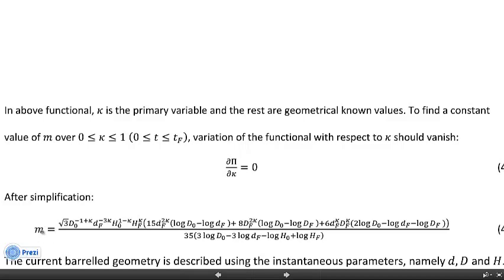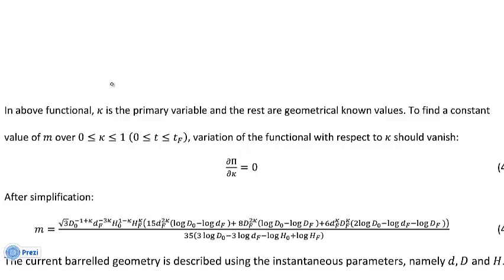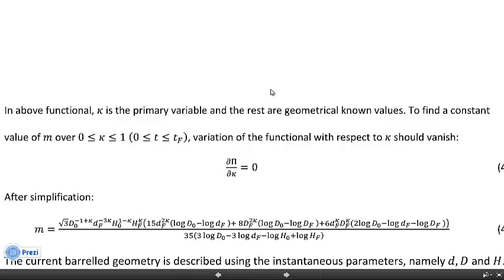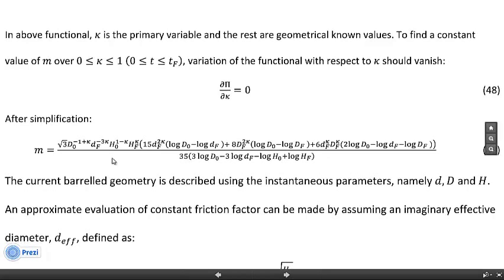We are now more confident: we have the value of M, and we have a solution to correlate the axisymmetric compression force and stroke. With M known, we are able to make a relatively accurate correlation between the constitutive expression and constitutive data obtained from the compression test.